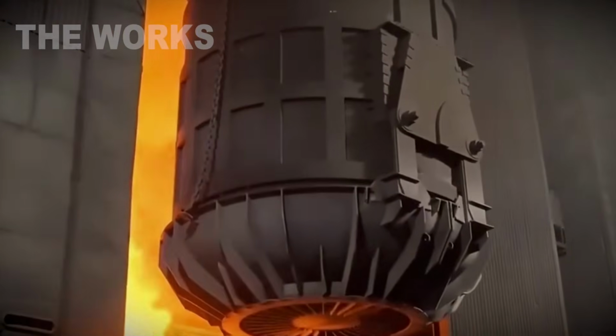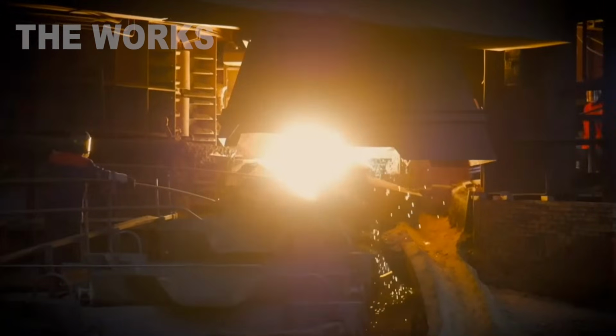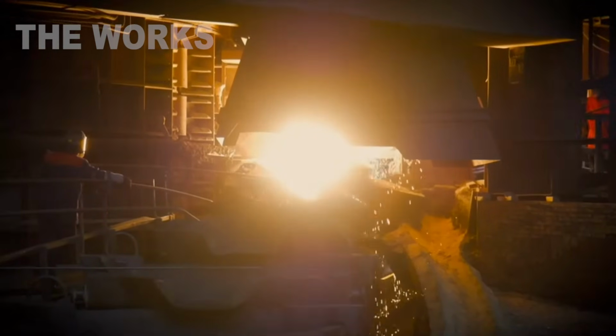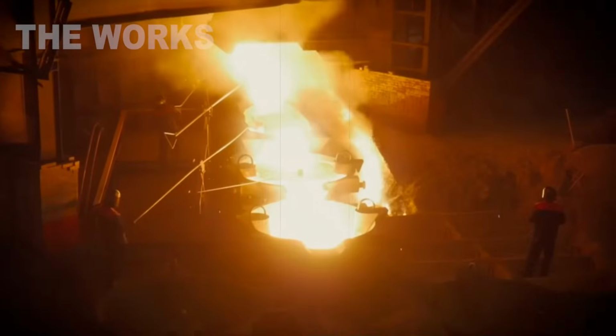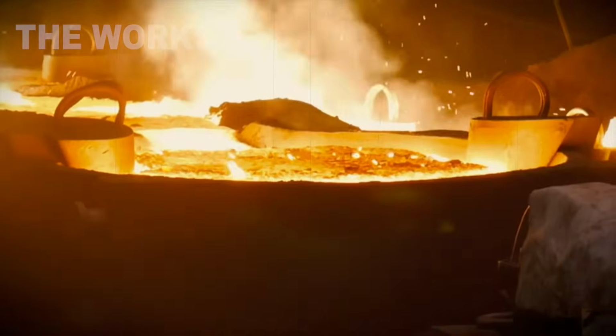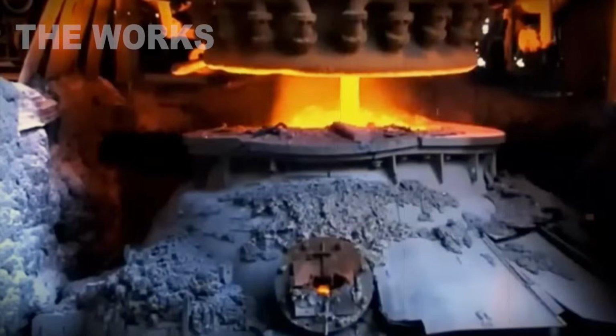Every 4 hours they tap the pig iron. They open the tap hole. Pig iron pours out like a river of fire. Temperature at 2,700 degrees. Color, bright orange. One tap, 300 tons. In 24 hours, the furnace produces 2,000 tons of pig iron.